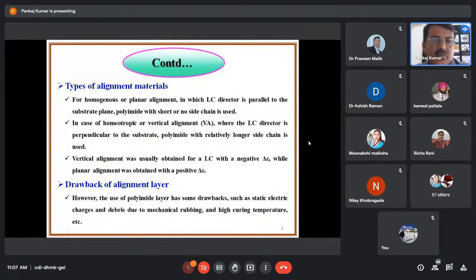So vertical alignment was usually obtained for a liquid crystal with a negative dielectric anisotropy, while planar alignment was obtained with a positive anisotropy liquid crystal. So in general, when we prepare the LCD device, for vertical alignment we usually use negative dielectric anisotropy materials, and for the planar alignment, we use positive dielectric anisotropy materials.